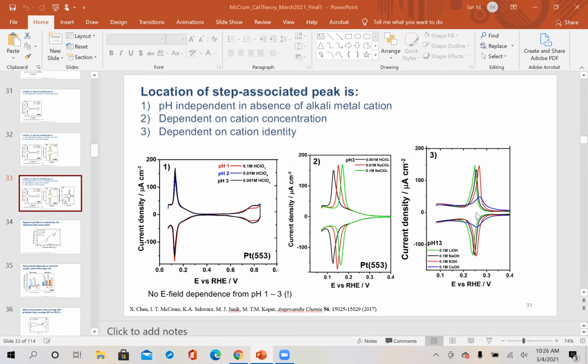In the DFT, we can capture this shift on the step by using a constant coverage of the cation and just changing the cation identity. If we model OH and water on the step with lithium versus sodium versus potassium versus cesium, we reproduce this shift that we observe experimentally. I expect, again, that the interaction is mostly electrostatic. Since they all have the same charge, probably it has to do with the size of the cation. That's going to affect the magnitude of the local field. But I can't point to some number that proves that.